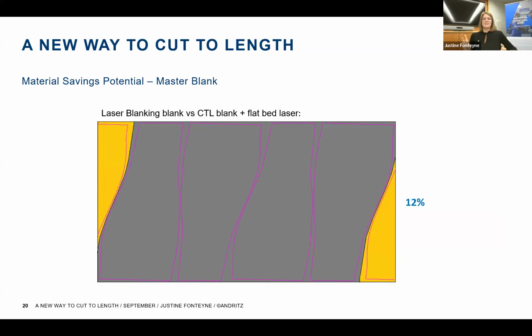Another example would be intelligent master blanks. So we regularly see that rectangular blanks are used in flatbed laser processes afterwards to cut the actual part. And what we have here as an example is that you are not using the full rectangular blank, but a multiple nesting of the parts you want to get and make an intelligent crosscut here. So that means you would not have a rectangular blank, but this gray area as a new blank to introduce to your flatbed laser. And then you could, same with the rectangular blank, cut out 4 of those parts, but you can also use the corners for the previous intelligent blank or the next. So you could save 12% of material.